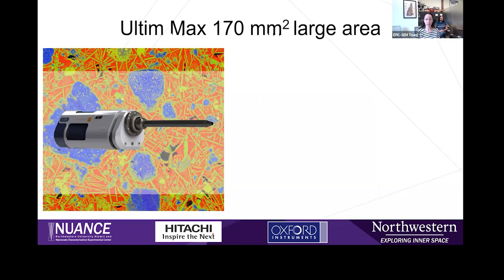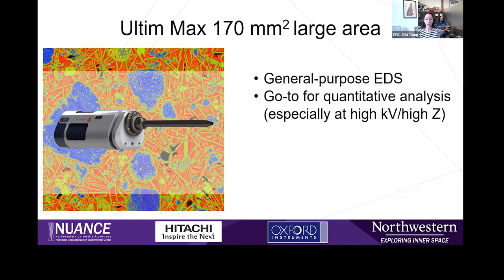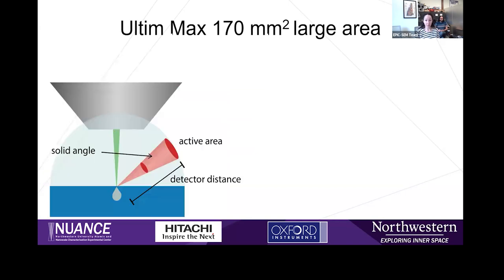So first, I want to talk about the Ultimax large area detector. You can think of this as kind of your general purpose EDS detector for this microscope, especially if you're doing your sort of typical high kV EDS or more quantitative analysis. This detector is from Oxford's Ultimax line of detectors, which uses kind of high-end technology to give superior speed and sensitivity without compromising on accuracy. On top of that, this particular detector from this line is their biggest at 170 millimeters squared.